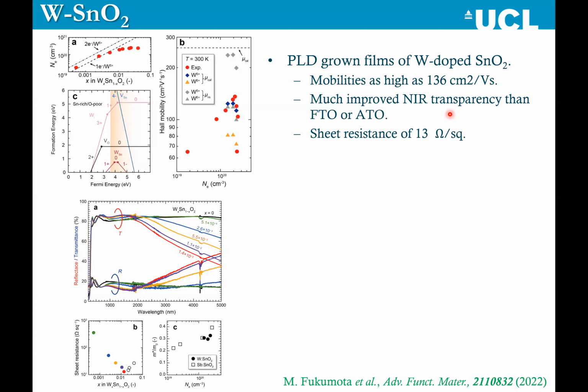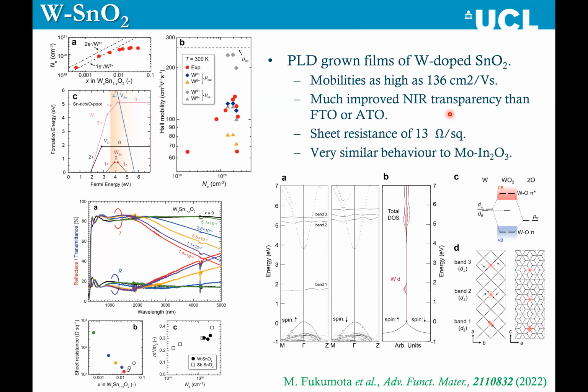Again, more transparency in the NIR, so exact same mechanism as previously. Again, band structures show you a very similar picture. One occupied D state in the middle of the band gap, meaning that's why it's tungsten 5+. The other unoccupied D states are high up in the bottom of the conduction band, way away from the conduction band minimum, no interaction, so maintaining the high mobility.